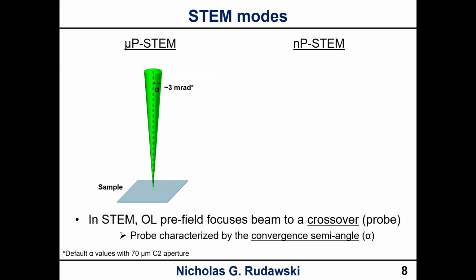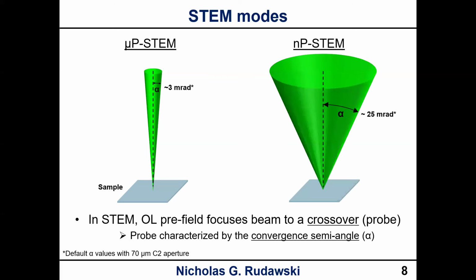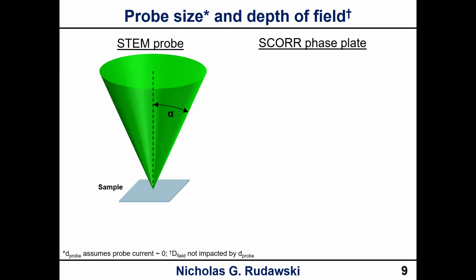But anyways, if we look at the case in nanoprobe, you're talking about a much larger value for your convergent semi-angle. And I say large here, right? 25 millirad, that's about 1.5 degrees, because 17 millirad is a degree. But that's still about a factor of 10. So this is the difference really between the modes: your convergent semi-angle. In microprobe, it's about an order of magnitude smaller.